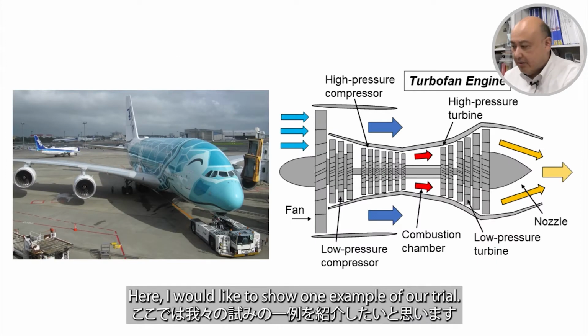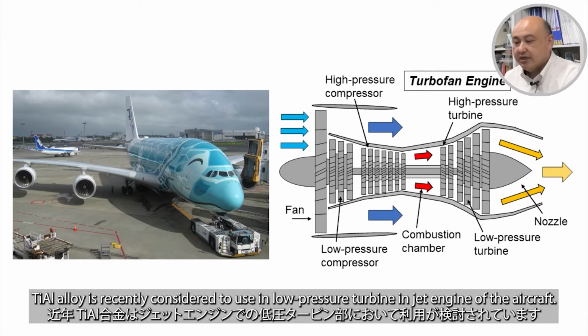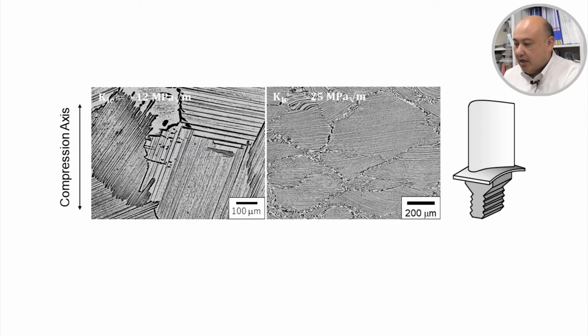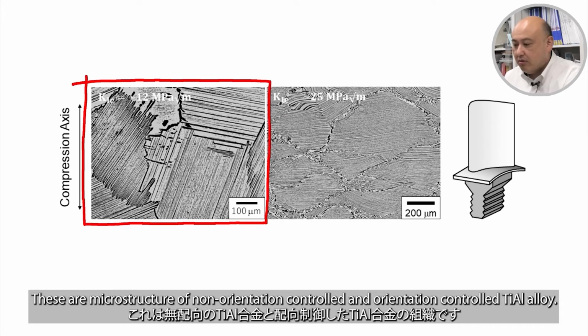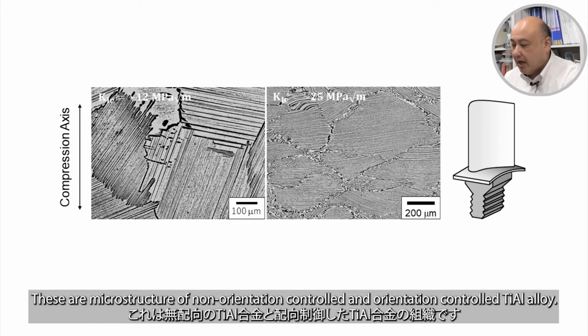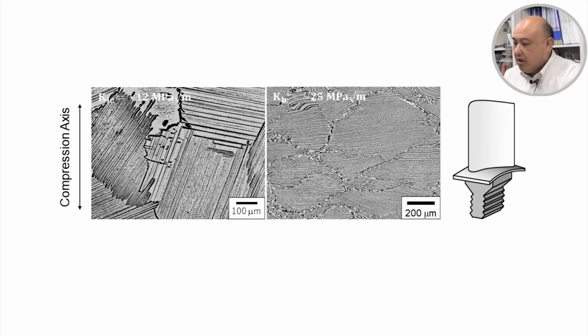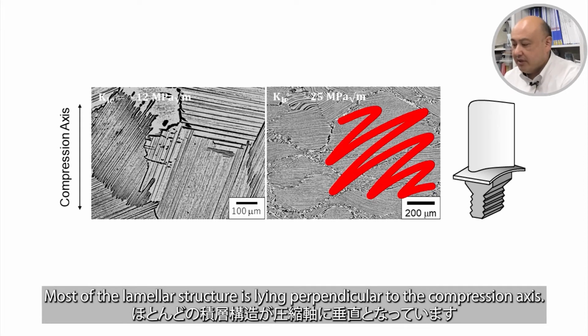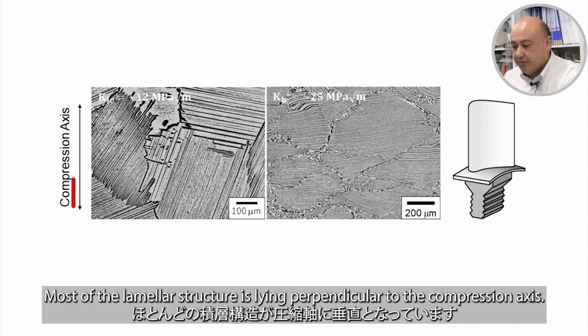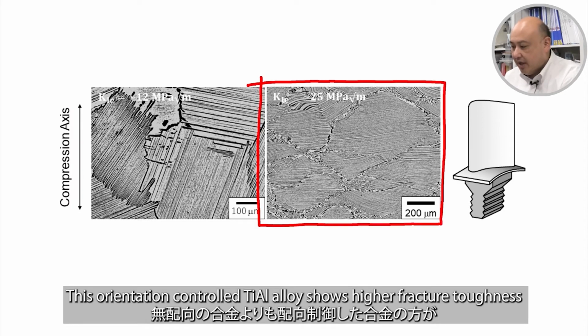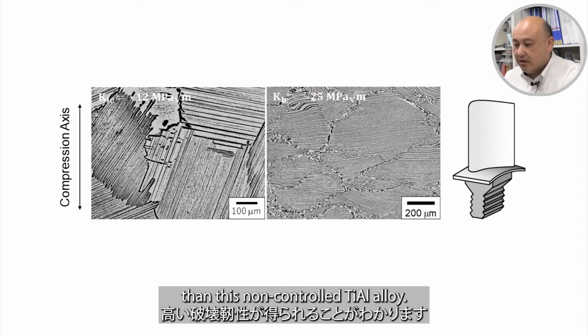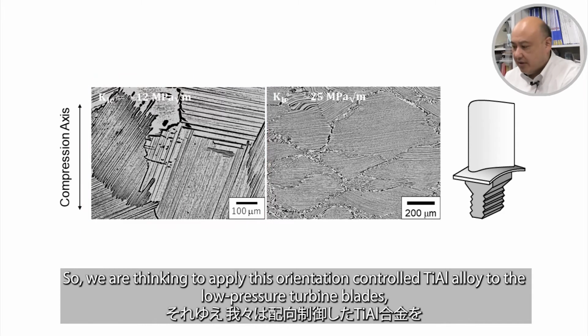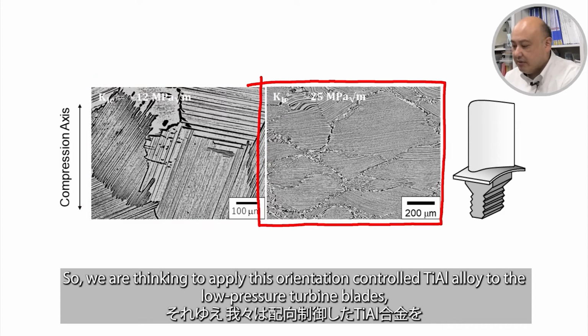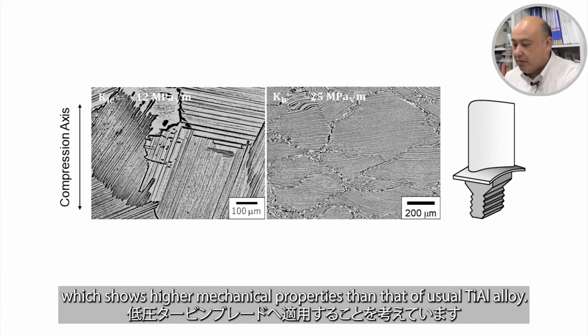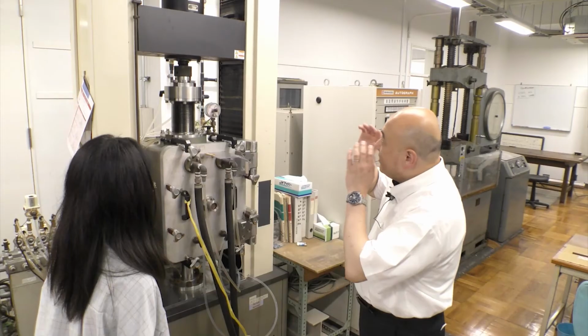And here I would like to show one example of our trial. Titanium aluminide is recently considered for use in the low pressure turbine of the jet engine of aircraft. These are the microstructures of non-orientation-controlled and orientation-controlled titanium aluminide alloy, obtained by high temperature processing. Most of the lamellar, a kind of multi-layered structure, is lying perpendicular to this compression axis. This orientation-controlled TiAl alloy shows higher fracture toughness than this non-controlled TiAl alloy. So we're thinking of applying this orientation-controlled TiAl to low pressure turbine blades, which shows higher mechanical properties than that of usual TiAl alloy. This is our equipment.